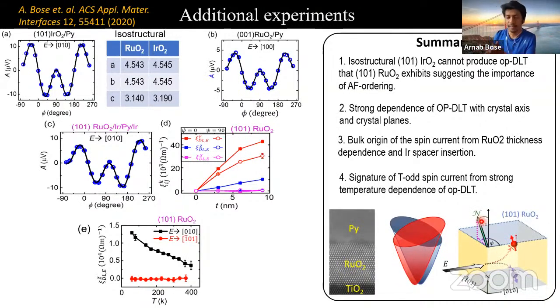So let's summarize all this together. In this work, we are doing spin torque measurements in high quality MBE grown ruthenium dioxide and permalloy bilayers. We observed tilted spin current, which is consistent with the theoretical predictions of the spin split bands of ruthenium dioxide. We keep in mind that both time even and time odd spin current can produce such tilted spin current, but the time odd spin current is predicted to be an order of magnitude larger. And we find an indication of time odd spin current because we see a substantial increase in the spin Hall conductivity as the resistivity of the material decreased. So this is a summary of this work.